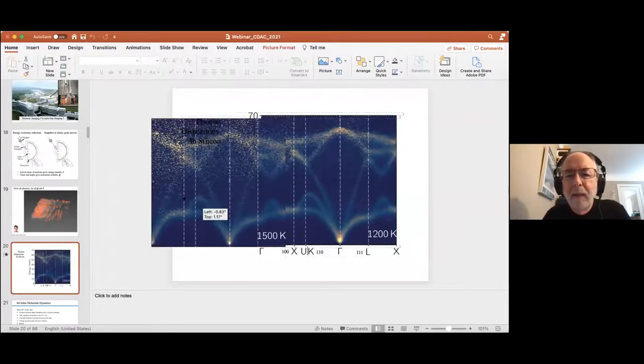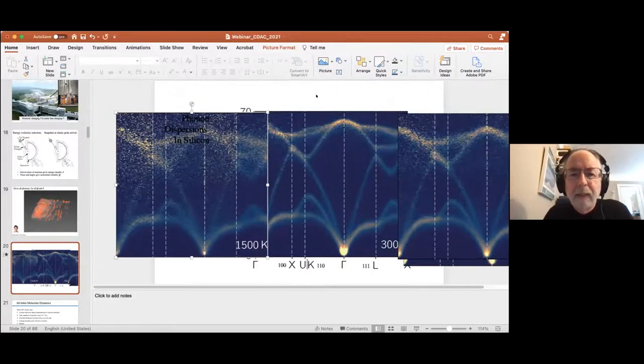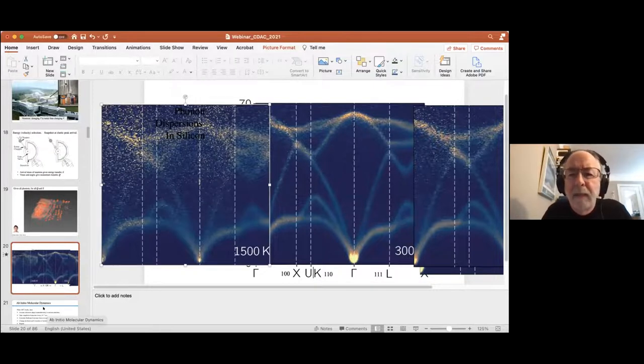Let me show you how they change a little bit with temperature by going down to room temperature and up to 1500 Kelvin. These are energy vertically, and horizontally is the direction in the reciprocal lattice, starting from the reciprocal lattice points at gamma out along the high symmetry directions. Now you can kind of see that there's a broadening and a decrease in the energies of these optical modes of silicon. The transverse acoustic modes down here also soften with temperature. And we can get a fair amount of detail on the phonon dispersions from data like this. And we've gone ahead and measured the thermal shifts of the different phonons, and they all have different personalities. But mostly they soften with temperature.